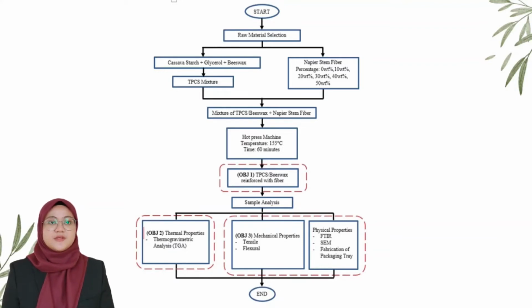The process starts with harvesting the raw material, which is Napier grass. Then the process continues with mixing the cassava starch, beeswax, and glycerol to form the TPCS mixture. The mixture will then be pressed using a hot compression machine for 60 minutes. The process continues for 0, 10, 20, 30, 40, and 50% of fiber content. Next, the samples will undergo various types of analysis such as tensile, flexural, TGA, FTIR, SEM, and lastly the fabrication of the biodegradable packaging tray.